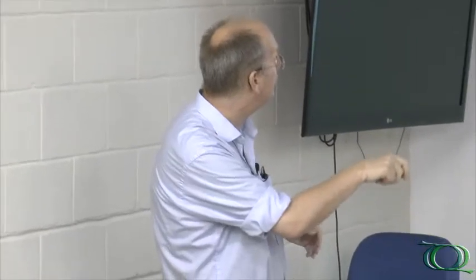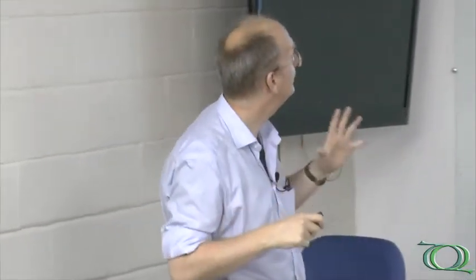But the real surprise was then if we change the amount of acid, it's also changing the signal. If I take a little bit more acid, nitric acid, the signal is getting bigger. And that really shows that this is not a solid state process. What we see is basically iron 3 is reduced to iron 2, but it's actually reduced in solution. So with the acid, there's always a small concentration of iron 3 in solution, and that's the active component.